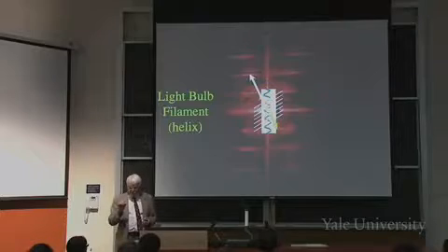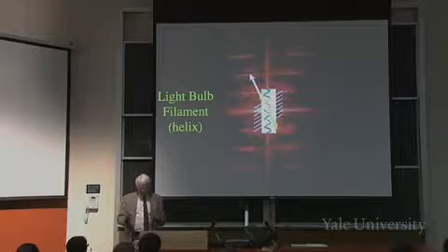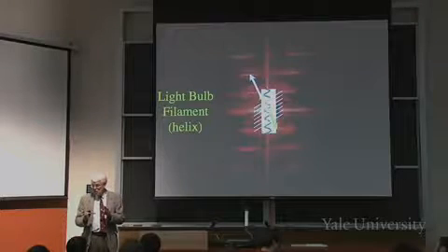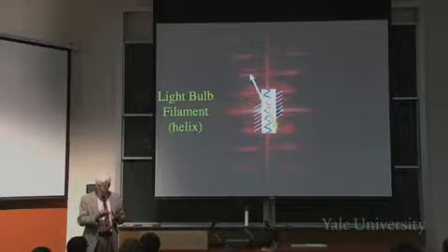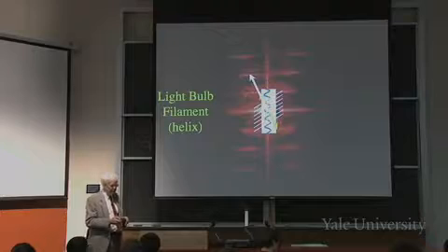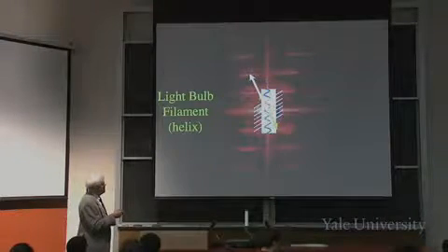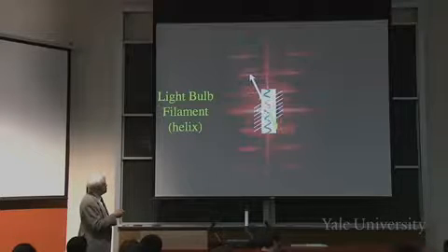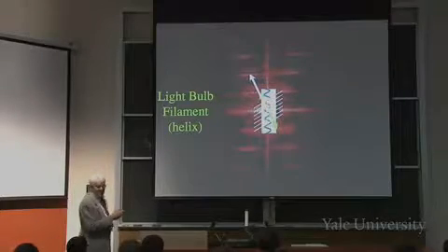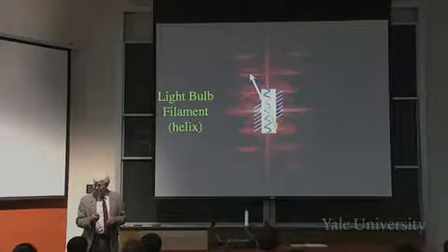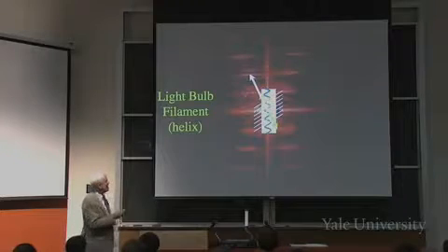And the reason is that there are two things that have to do with the brightness. One is how much density there is on the planes versus how much there is between the planes, right? And we see here that, say, take the original yellow one, all this stuff is nearly on the plane, and halfway between the planes, there's not very much, just a thin cross-section of the wire, okay?